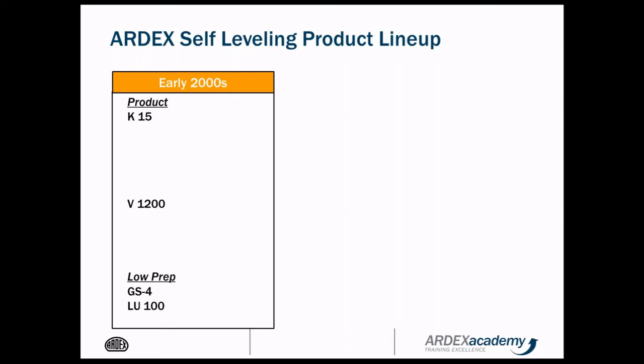So it can be poured over the weak gypsum material without failure because it's a low stress, low tension, virtually no tension type material. But the difference with GS4 compared to existing gypsum is it has a very high strength, compressive strengths of over 5,000 psi, tensile strengths